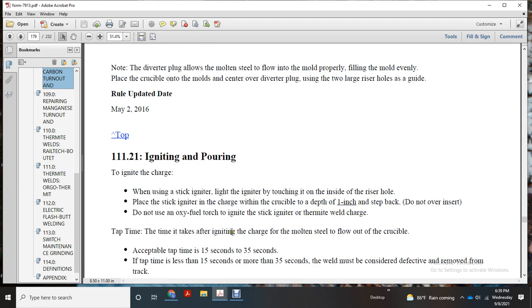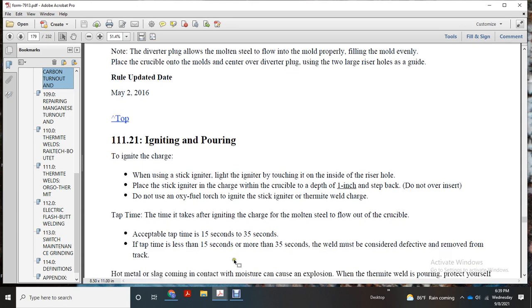Tap time is the time it takes after igniting the charge for the molten steel to flow out of the crucible. Acceptable tap time is 15 to 35 seconds. If the tap is less than 15 seconds or more than 35 seconds, the weld must be considered defective and removed from the track.